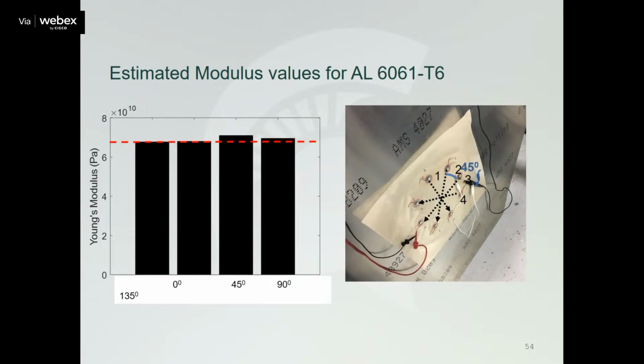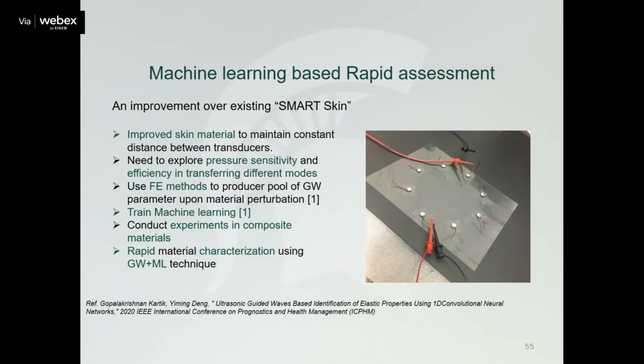Okay, this just shows you some results of estimated Young's modulus for this aluminum 6061 T6 material, and for different angles, you can actually estimate the Young's modulus very well using this smart skin. Machine learning can also be applied here, so you can improve that, using numerical simulation to generate a lot of data, and you can also use the smart skin to capture the real data. And using guided waves plus machine learning technique, you can have a rapid material characterization. Of course, you have to train the model well and use that to get the material characterization done, assisted by the AI.